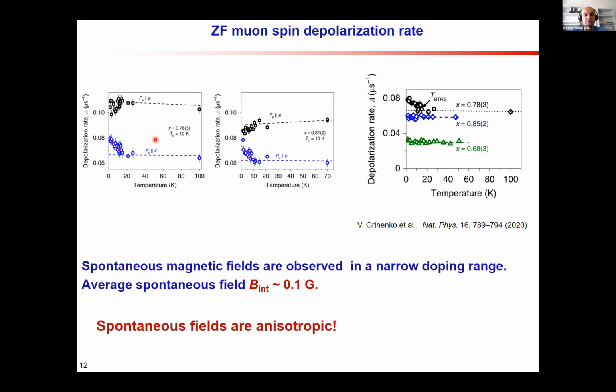And what is interesting, and really new for this kind of superconductors, is that the spontaneous fields are anisotropic. We observe that the clear relaxation rate enhancement was observed only for the direction of the muon spin polarization along the c-axis. When we looked at other directions, we could not find a change of the relaxation rate. It indicates that these fields are aligned in the AB plane.